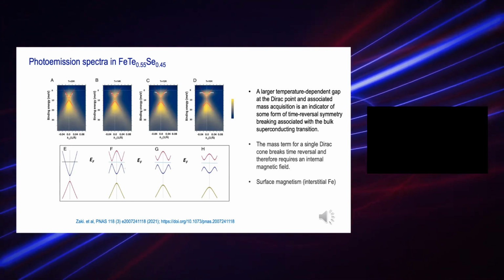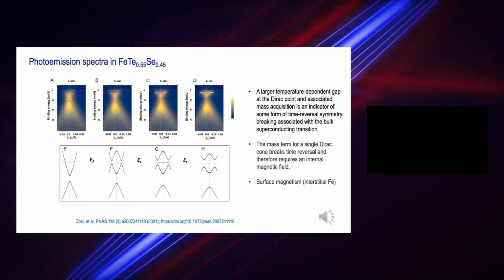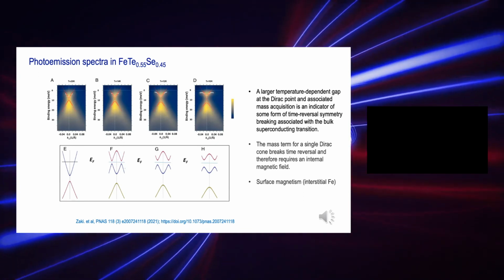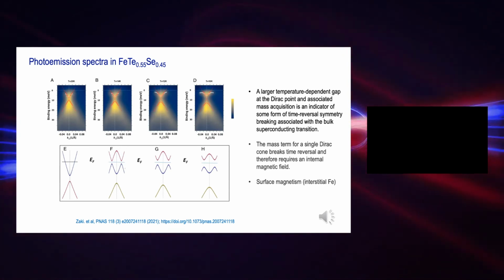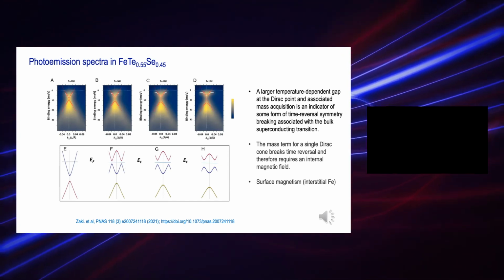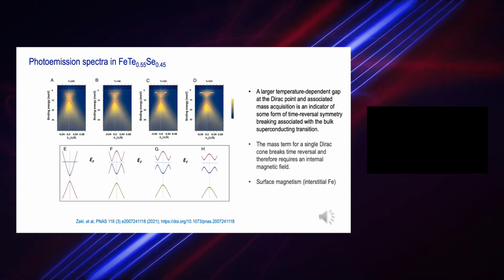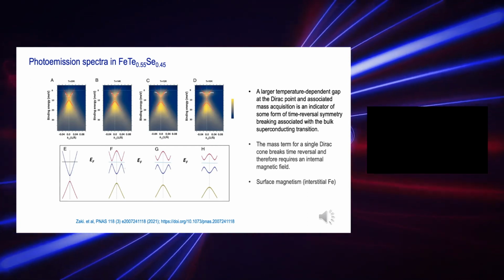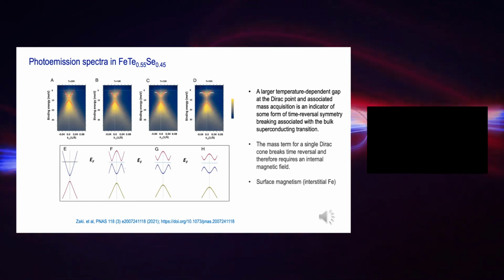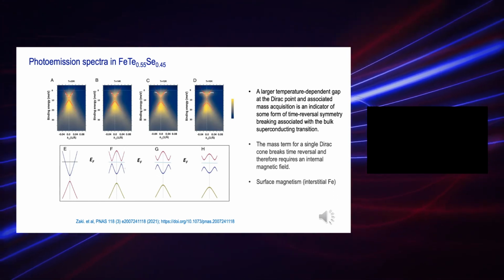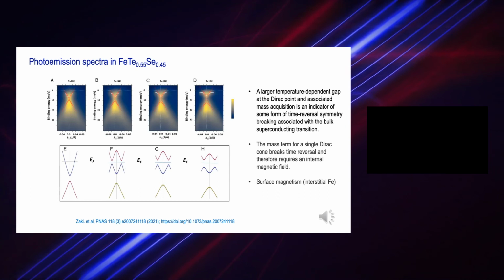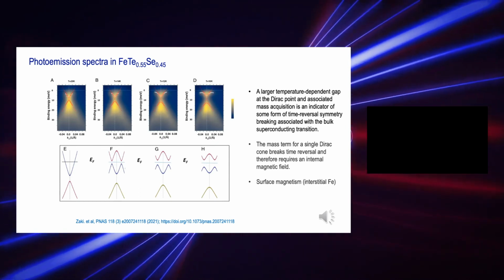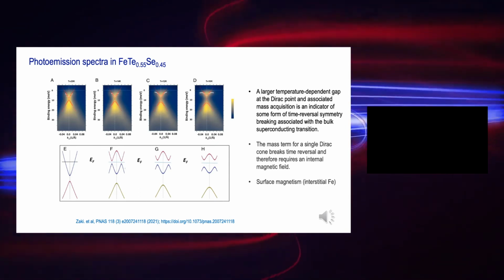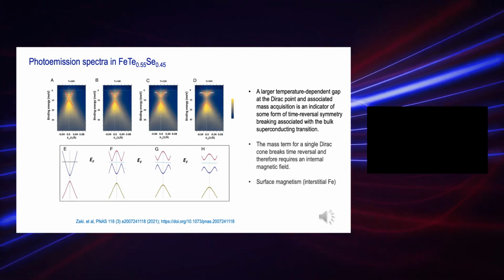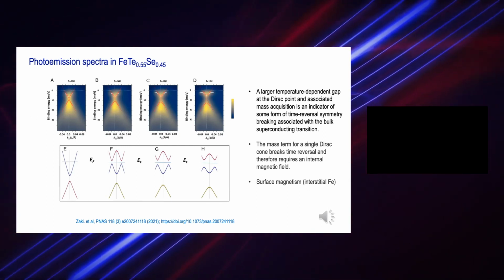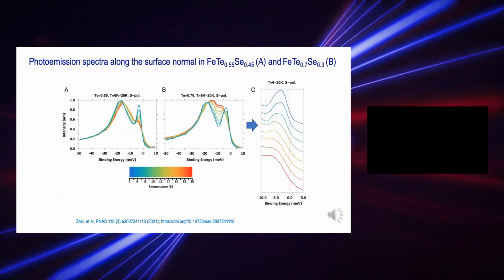First, you see these Dirac dispersions that represent the topological nature of the system with a very low chemical potential, and this is good for seeing the Majorana zero mode. And also the development of a large temperature-dependent gap at the Dirac point and associated mass acquisition is an indicator of some form of time reversal symmetry breaking associated with the bulk superconducting transition. And this signals they could have some surface magnetism, possibly coming from the interstitial irons.